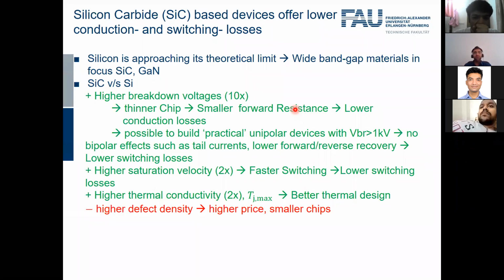And the major disadvantage or challenge of silicon carbide is the higher defect density. So silicon carbide today is manufactured, or the raw wafer is manufactured in a different process compared to silicon. And this also makes the defect density quite high on silicon carbide. Of course, this is drastically improving over the years, but still it's not at the same level as silicon. And therefore, the size of the silicon carbide chips are rather limited compared to silicon devices. And also the price of silicon carbide is rather high compared to silicon devices. And I think this will remain at least for the years to come. Silicon carbide will be more expensive than silicon for the same chip size.